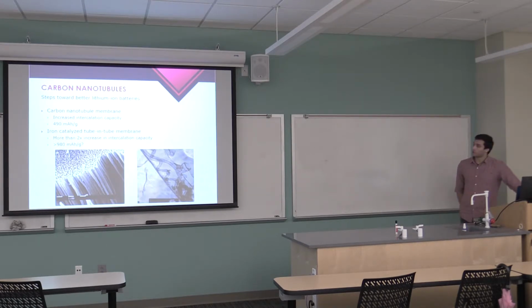So the first thing I'm going to cover is the carbon nanotubes here, or carbon nanotubules, excuse me. Basically what they did is they used a chemical vapor deposition process to put carbon nanotubes into a porous aluminum membrane. And on top of that, they used an iron catalyzed reaction to put smaller nanotubes into those tubules. So you can see the picture on the left, that's at the 1 micrometer scale. And that's the initial porous membrane from the carbon nanotubules in the aluminum structure. And on the right is a 50 nanometer scale, and that's a picture of inside those tubules from the left.